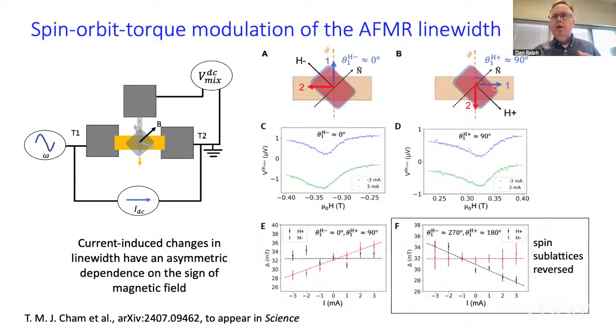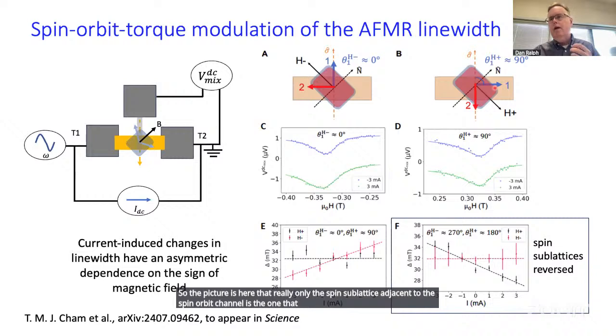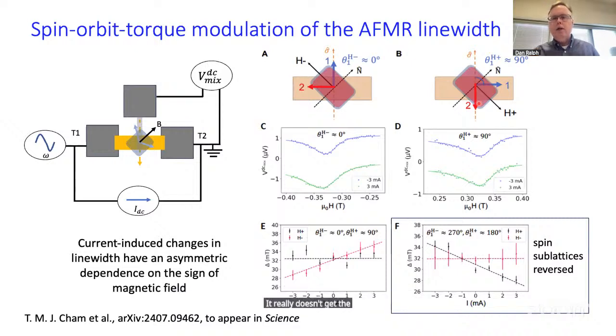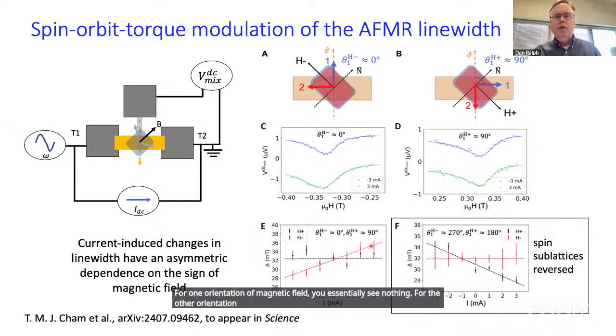So the picture is that really only the spin sublattice adjacent to the spin orbit channel is the one that is affected by the spin orbit torque. The second spin sublattice just doesn't see that. So even if the second spin sublattice is oriented favorably relative to the spin orbit torque, it really doesn't get the advantage of that anti-damping torque. So the bottom line is that if you think about the change in the line width as a function of DC current, for one orientation of magnetic field you essentially see nothing. For the other orientation, you see a strong dependence of the line width on the current from the anti-damping torque.